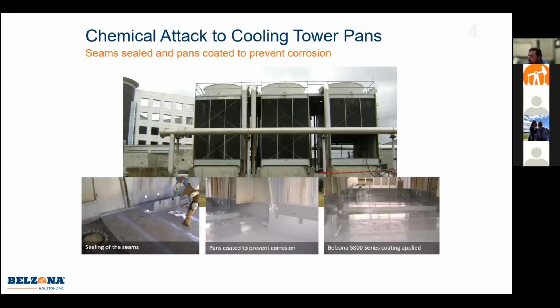We're going to jump back into the top here on cooling towers. But right here is just an example of a little package unit we've done, where if you start on the bottom left, you can see where we blast clean the surface. And right here is what we did. We sealed the substrates with a flexible membrane that we use for the seams. Your towers vibrate a lot and they do move and shake during service. So this flexible membrane helps hold that in, per se. And then, of course, the middle and far right, that's just showing you each coat of our 5800 series Belzona. But also we do tailor-make based on your temperature and service that you want to see.